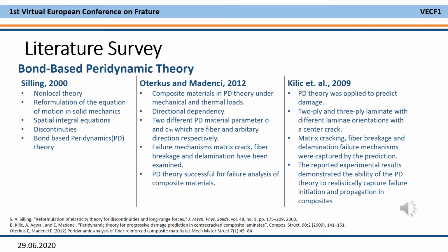Then Oterkus and Madenci presented an application of peridynamic theory to predict how damage propagates in fiber-reinforced composite materials under mechanical and thermal loads. Problems have been analyzed in fiber direction and arbitrary directions. Therefore, two peridynamic bond constants have been determined for each direction. Failure mechanisms such as matrix crack, fiber breakage, and delamination were examined. They came to the conclusion that peridynamic theory is successful for failure analysis of composite materials.